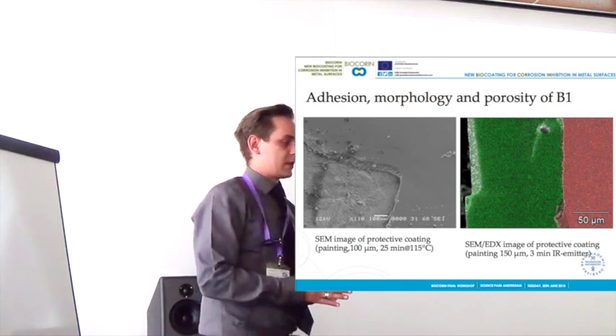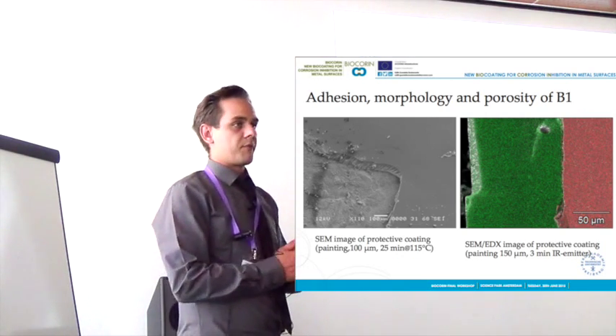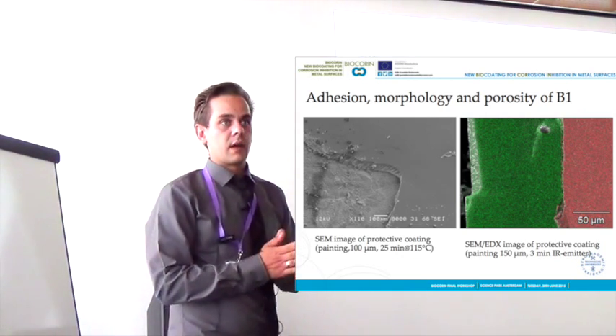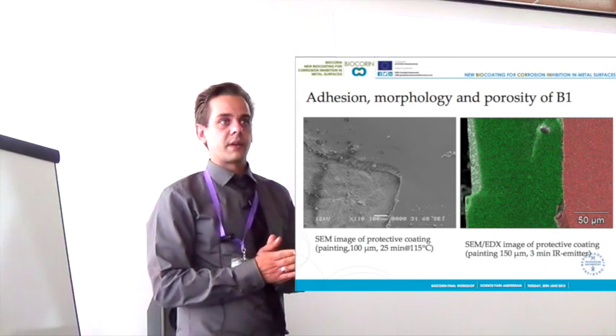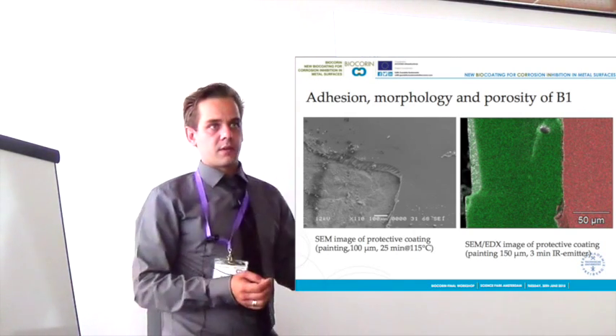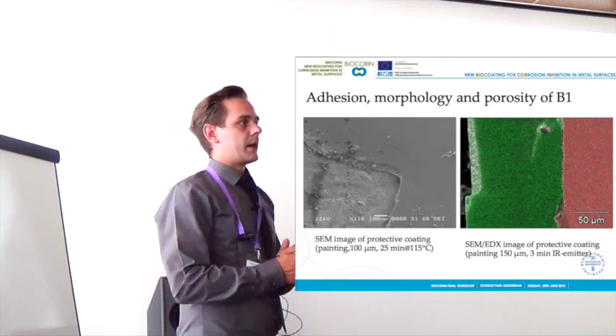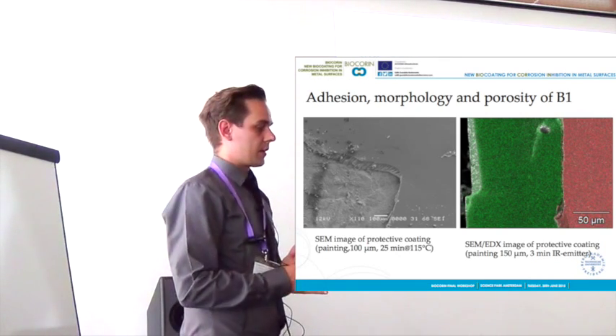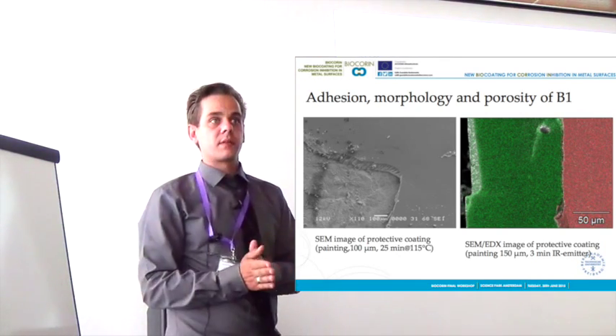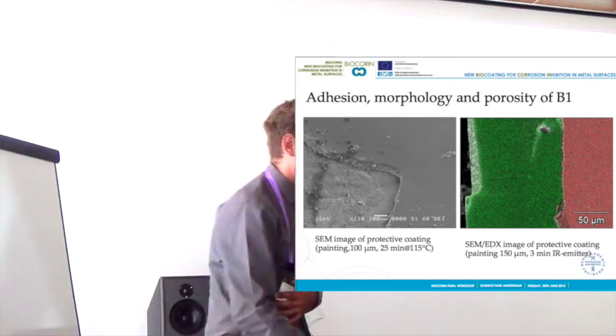Here we have the adhesion, morphology, and the porosity of B1, and as you can see, we have a quite dense coating without any defects, holes, or cracks that can decrease the corrosion protective properties of the material.